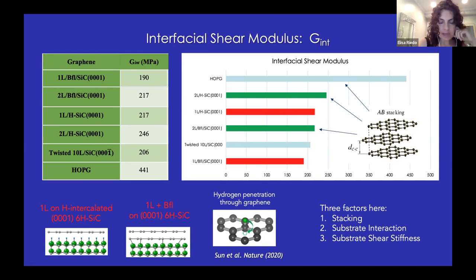So the explanation that we have here is given by the presence of this hydrogen. What we believe is happening is that this hydrogen is actually hindering the motion, whereas the one layer on buffer layer is a non-commensurate structure. And we think that also it's a mix, TEM studies indicate that they have a mix of AB and AC stacking. So it's a disordered, if you want, carbon-carbon interface. And so we think that that's the reason why this has such a low interfacial shear modulus, compared to this structure here that is, on the other hand, hindered by the presence of hydrogen.